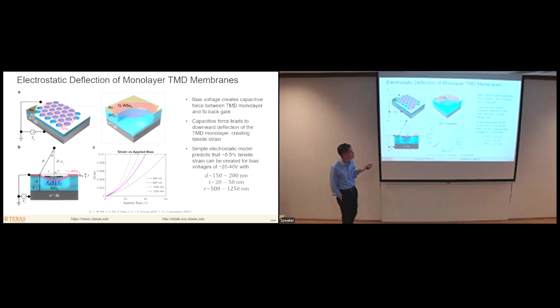And if we do some simple modeling of this, where we equate the energy associated with strain in this material for a given deflection with the electrostatic energy of this capacitive interaction, then what this would predict is that for the typical dimensions of the structures that we're making here, we can get to strain on the order of maybe a few tenths to 0.5%, which is sufficient for observing single photon emission at backgate bias voltages on the order of 20 to 40 volts, which is very achievable.